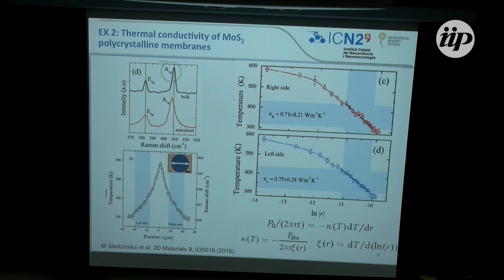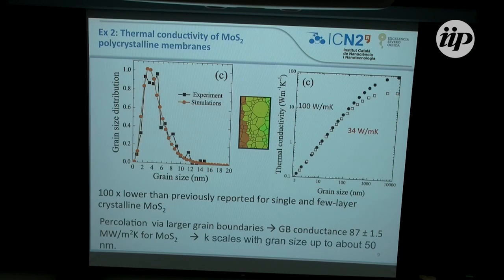Polycrystalline means that it has grains. Grains means that you have a distribution. And so we ran, first of all, SEM analysis of the grains. We saw a distribution of those. We saw that we had a majority of grains in the few nanometers, so 3 to 5. And the model that was made took into account percolation of phonons in these grains. The important bit is that there is a gradient of grains, and this actually led to the difference between the left and right values of the thermal conductivity.